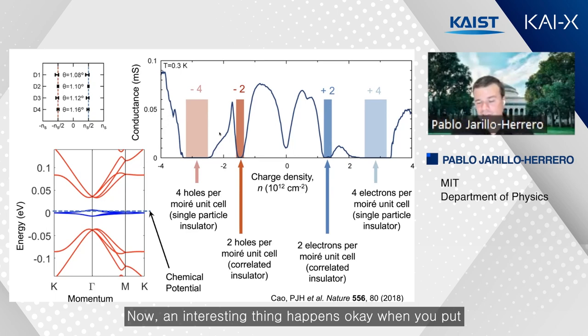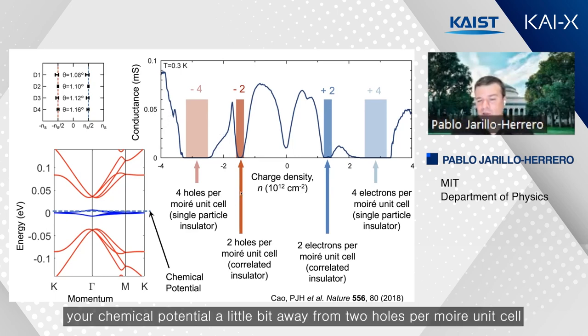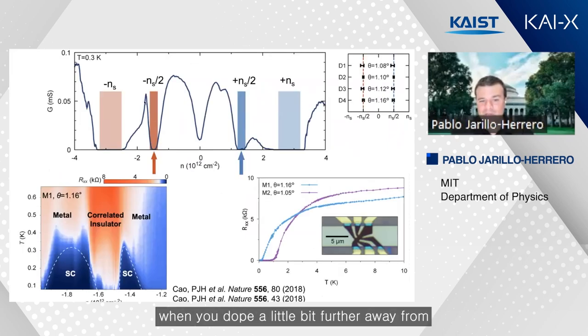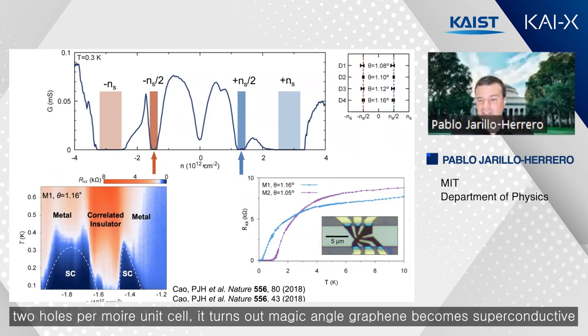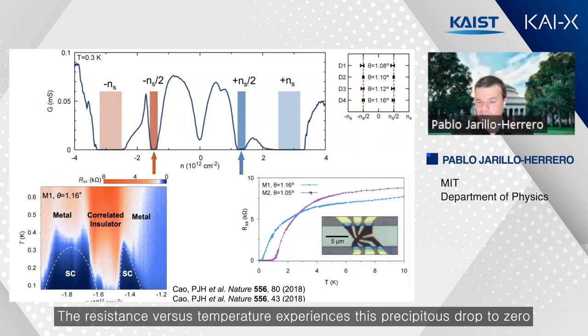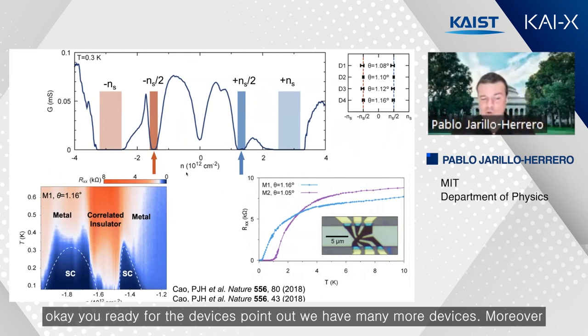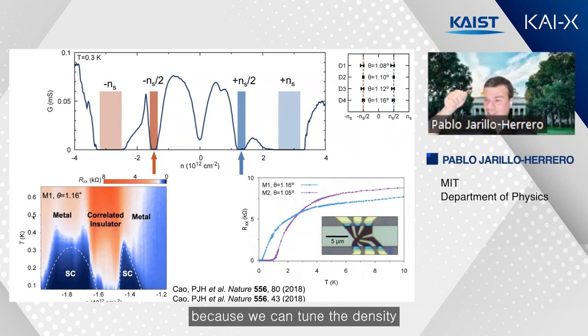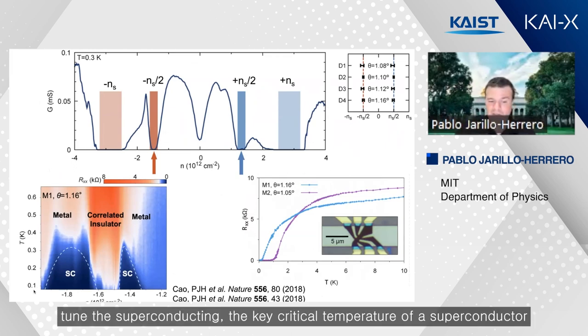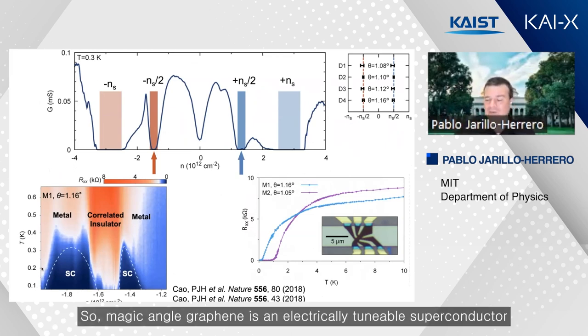Now, an interesting thing happens when you put your chemical potential a little bit away from two holes per moiré unit cell or two electrons per moiré unit cell. In particular, when you dope a little bit further away from two holes per moiré unit cell, it turns out magic angle graphene becomes superconductive. The resistance versus temperature experiences this precipitous drop to zero. This is the data for two devices; by now we have many more devices. Moreover, because we can tune the density with our gate voltage, we can tune the superconducting critical temperature of a superconductor. So magic angle twisted bilayer graphene is an electrically tunable superconductor.